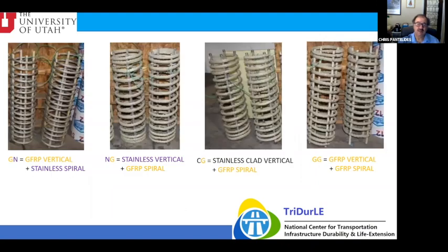So here you see the 4 combinations. We can call these hybrid, except the last one is all fiberglass, so it's not a hybrid. The first one, you see the GFRP vertical and the stainless spiral, and the other 3 all have fiberglass spirals. So it's the NG, which is stainless vertical and fiberglass spiral, stainless clad vertical and fiberglass spiral, and then all GFRP. Here, on the stainless clad, you can see at the end we have some protective caps, so the corrosion will not go through the section where the black steel is exposed.